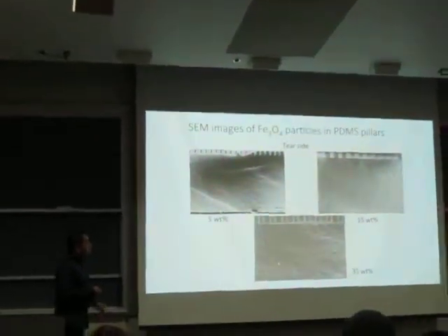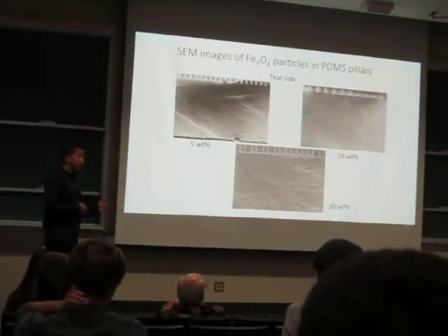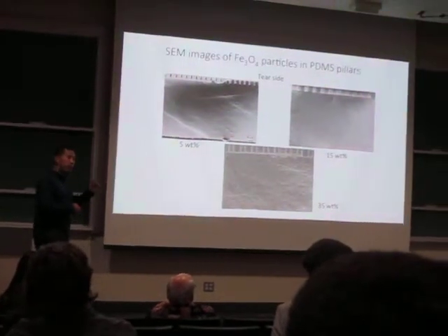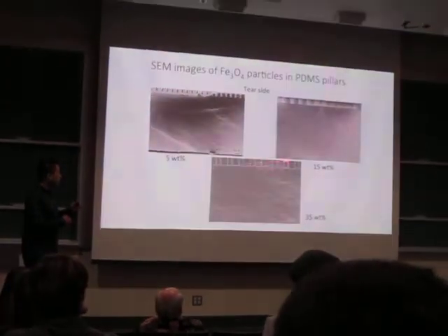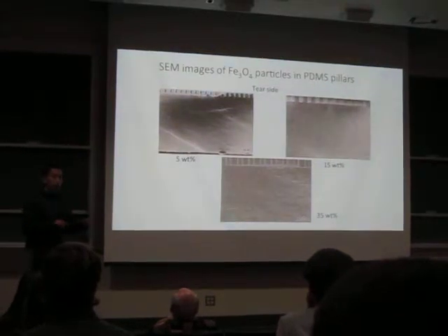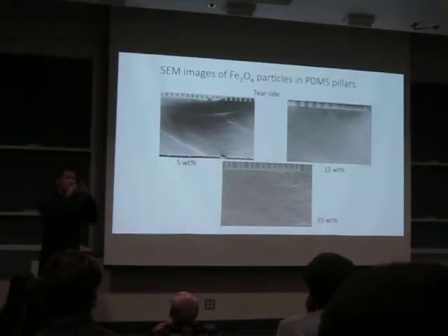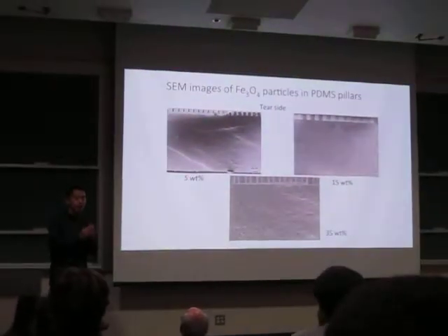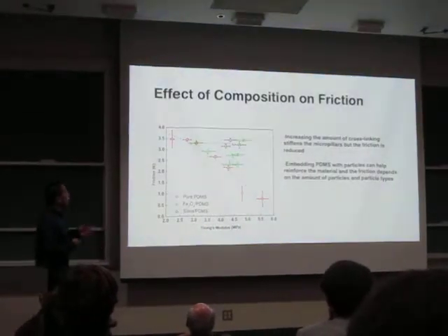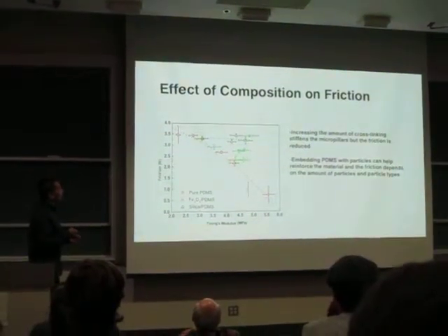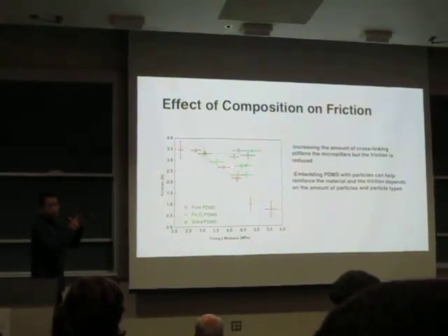So we see here, it's much more concentrated in this part compared to this part where it has pillars, which means there's a concentration gradient. Here it's very concentrated, and here it's less concentrated. So the middle part of the sample is very hard, and the edge part is very soft. So we create a situation that is very soft on the edge, but very strong in the middle, which yields the result that it drops here and then goes back up, because it's very soft on the edge.